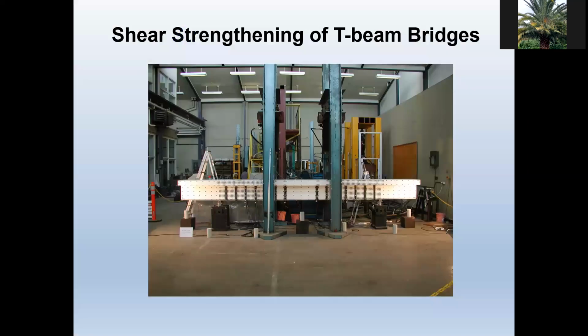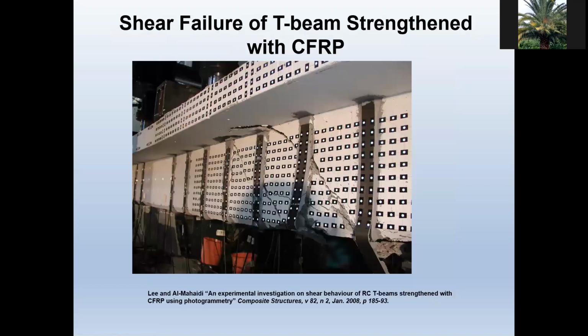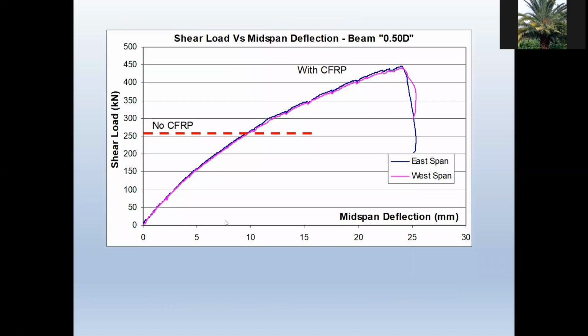Typically, we have done some tests on these beams, full-scale beams, many, many years ago. And so you see these vertical strips are carbon fiber strips, okay? And we tested this and we published the work at the time, and you see that without the strengthening, the capacity of the beam in shear was about 250 to 260 kilonewton. When we used the CFRP, we were able to go to about 450 kilonewton, much higher capacity than for the unstrengthened beam.